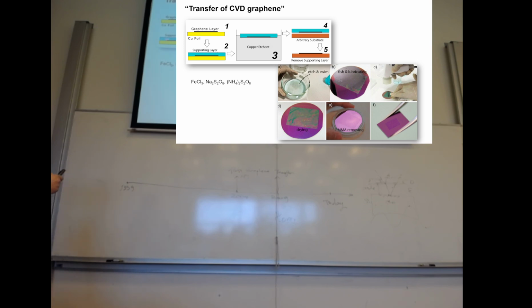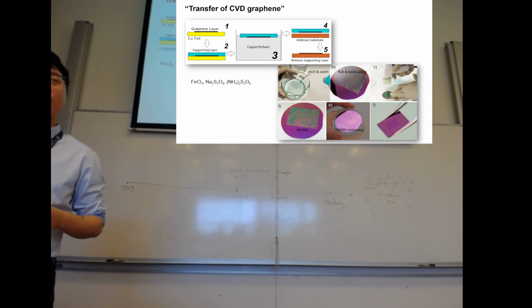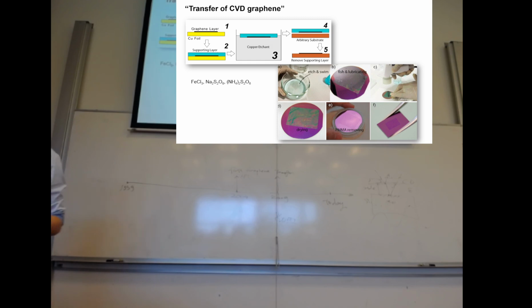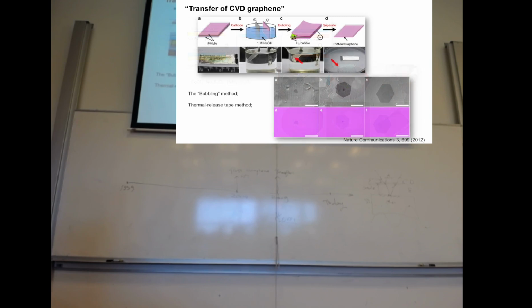So people have to use a supporting layer, even nowadays, to transfer two-dimensional materials. Then you just dissolve that in acetone. So again, you will have a very clean one. Looks clean, but if you look under the microscope, you will see there are a lot of cracks and holes and many residues of PMMA, for example. So this is the way people do graphene production, even nowadays, sadly. So that's the way it is.